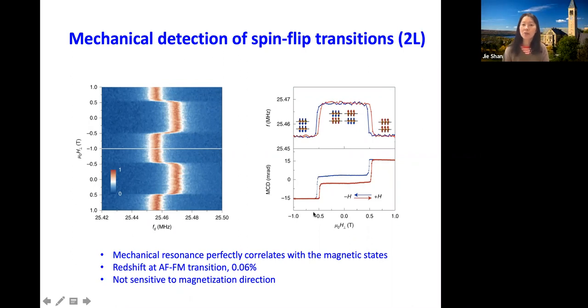So mechanical resonance is perfectly correlated with the magnetic state, as you can see from those two pictures. And again, this is due to hysteresis, that's a first order transition, and that's expected. And the redshift is on the order of less than 0.1% in terms of frequency. But the Q is large enough to allow us to see this very clearly.